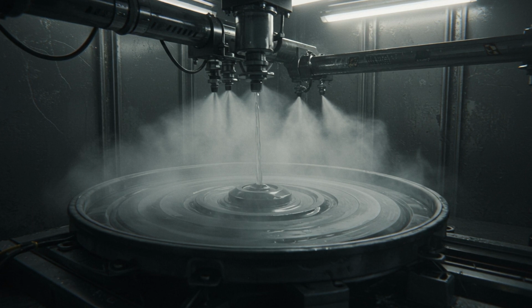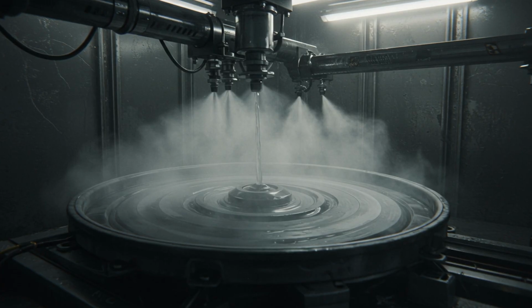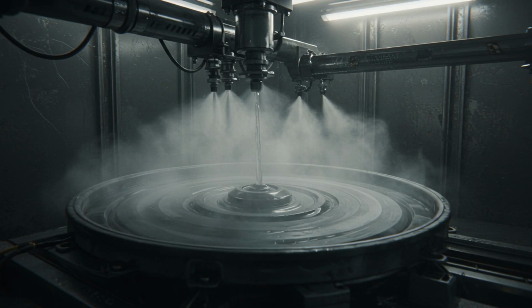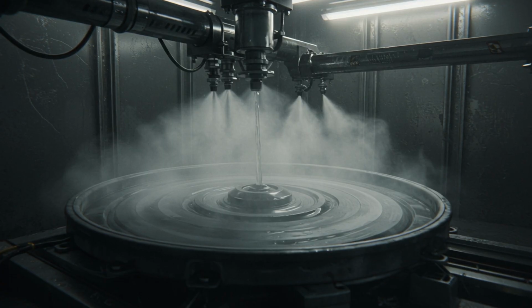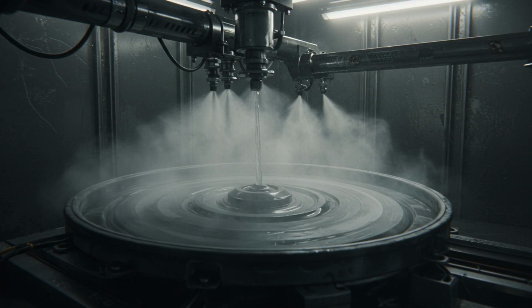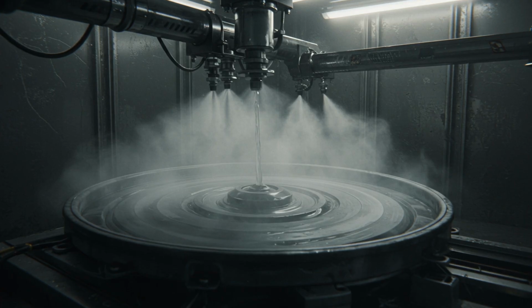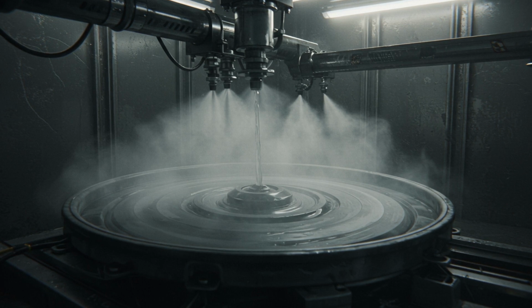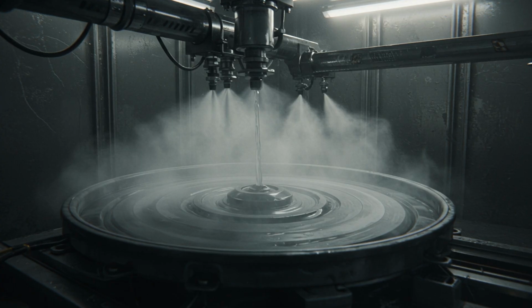Inside a clean room environment to prevent dust contamination, automated robotic arms spray a precise layer of this primer onto the rotating pans. The thickness is monitored down to the micrometer, usually hovering around 10 to 15 microns. If it's too thick, it will crack. If it's too thin, the top coat won't have enough to hold on to. The pans then travel through a low-temperature oven to flash off the solvents, leaving behind a tacky, ultra-strong foundation. This layer is the diplomat of the materials world, negotiating a peace treaty between the reactive metal surface and the inner, non-stick top coat. Without this specific chemical cocktail, the non-stick revolution would never have happened.